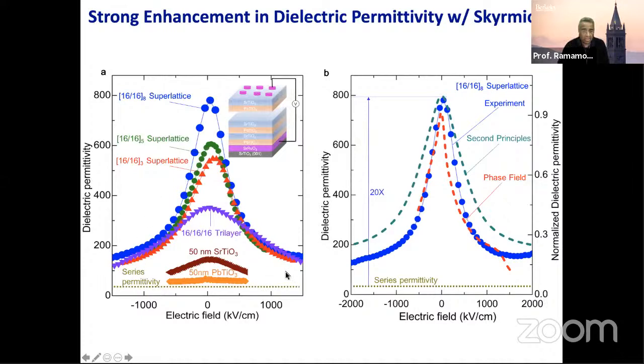The blue data is what he saw for the superlattice. He saw a permittivity of 800. We said, oh, that is too large. It cannot be possible. He measured multiple samples, etc. Always give a very large value. And very systematically, it'll change with the number of superlattice layers.